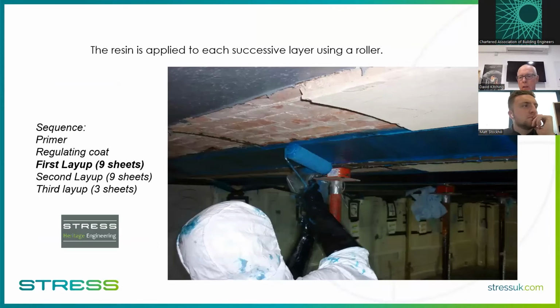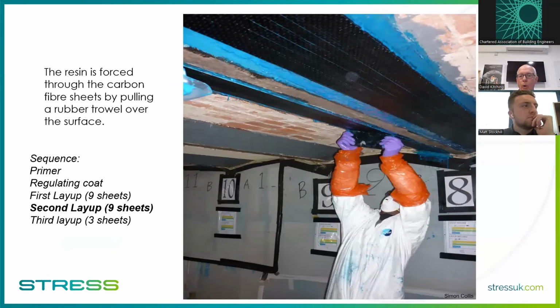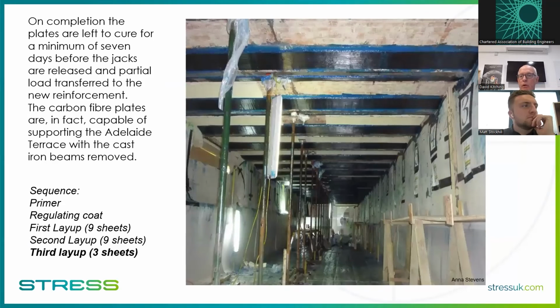Here we are applying the roll, so it's all wet on wet. So you go up with your carbon fibre, your resin, very much like wallpaper pasting. Up goes the sheet, and then you pull that resin right the way through the sheet. Push the sheet up to the next layer. We used blue for some reason. It was really so that we could see where it was going, and you go sheet on sheet on sheet until you've got all 21 sheets. There it is.